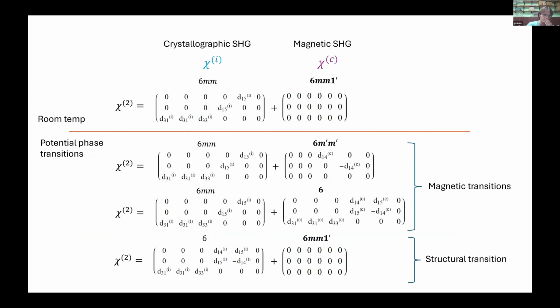So I want to quickly clarify the difficulty with the magnetic SHG. Fiebig in his papers emphasizes that you need the spectroscopy degree of freedom to do this reliably. And we did not have the equipment for this, the setup for this. We were hoping to avoid that because we expected a different point group that wouldn't conflict with the existing polar SHG signal, but you can see for the polarimetry we observe, there's a few different combinations of crystallographic and magnetic point group you can have that when you add them together, they overlap and they give the same tensor. And by the way, this is the Voigt notation. So the third rank tensor is reduced to the 3x6 matrix using its intrinsic permutation symmetry.